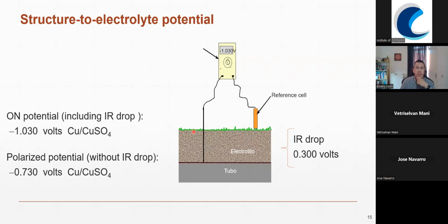For example, if we are on the field and we place the reference electrode and we touch the pipeline by means of a test station or a valve, we might have a reading of minus 1030 millivolts against copper sulfate. And if that technician is not aware that we might have IR drop, we could say we're in compliance, we're okay, because we need at least 850 and we have 1030. But in fact, we need to make sure that we are able to identify what's the IR drop, because, for example, we could have 30 or 300 millivolts as IR drop, then when we do the correction, we will realize that we are not in compliance.